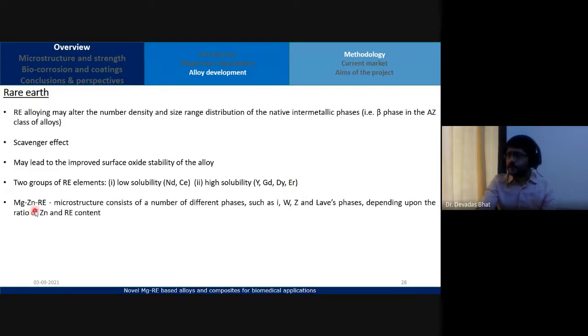We have developed ternary systems, Mg-Zn-RE, by playing with the composition. We also designed magnesium, calcium, erbium. The microstructure consists of a number of different phases, such as icosahedral phase, W phase, Z phase, Laves phase, depending upon the ratio of zinc and rare earth content. So with a different number of phases, you will have different mechanical behavior.